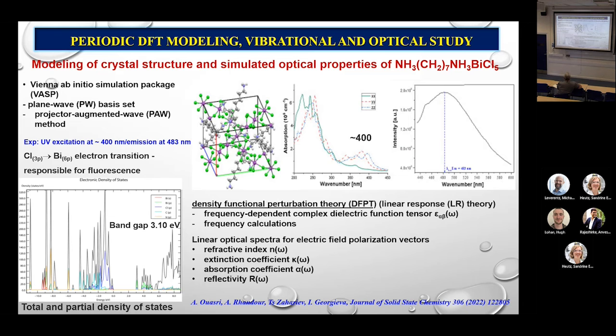Shortly, I would like to present another approach where the crystal structures are modeled and their optical properties were calculated using a periodic approach by means of the Vienna Ab initio Simulation Package and the plane wave set projector augmented wave method, on the basis of density functional perturbation theory and frequency dependent complex dielectric function tensor calculation. We can derive the linear optical spectra for electric field polarization vectors.